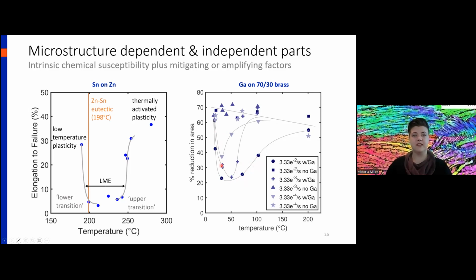So in all of these different systems, you see at low temperatures, you get very little ductility. Whereas at higher temperatures, your ductility is restored because of thermally activated plasticity. And that's true at different strain rates. That's true with and without gallium. So all of the no gallium samples fall along this line. All of the gallium samples fall along one of these three curves. And you can see that at each different strain rate, embrittlement is more or less severe.